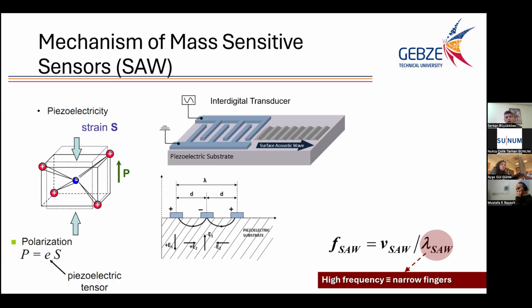Now suppose that you have comb-shaped electrodes on top of a piezoelectric substrate, and if you apply a time varying RF signal, you can create some displacement on the surface. And at a certain frequency, a constructive interference occurs for this displacement, and surface waves are released and propagate on the surface. The frequency of this propagation depends on the pitch size of the electrodes here. As you see, this is the relationship. So narrower fingers and narrower spacing between the fingers mean a higher frequency.